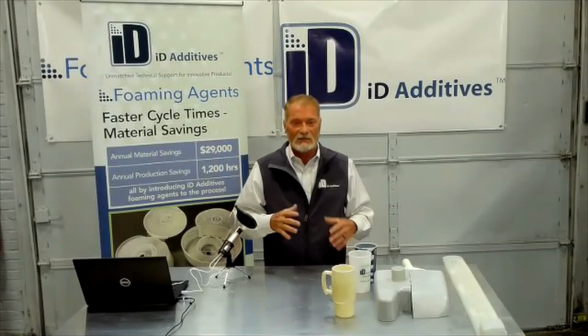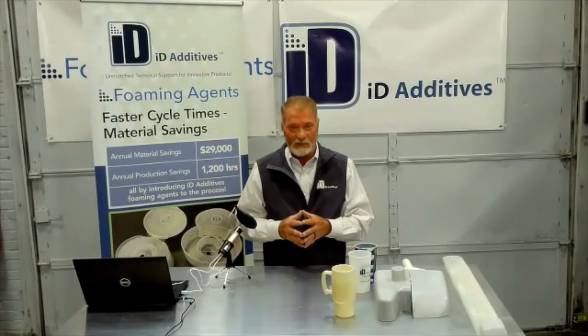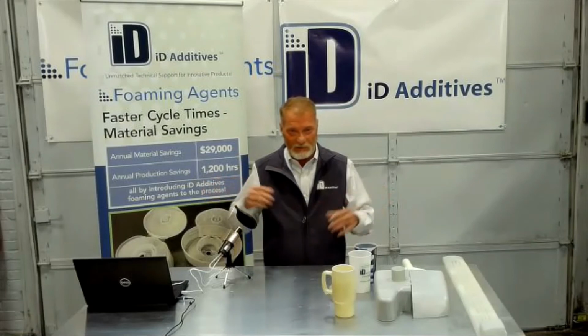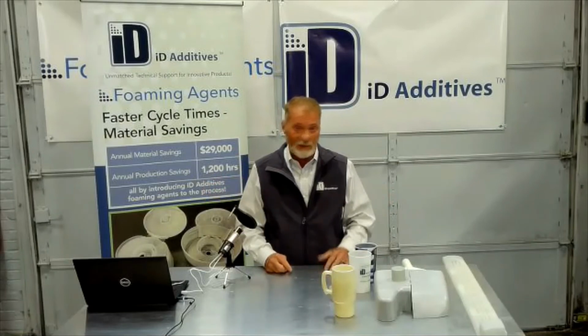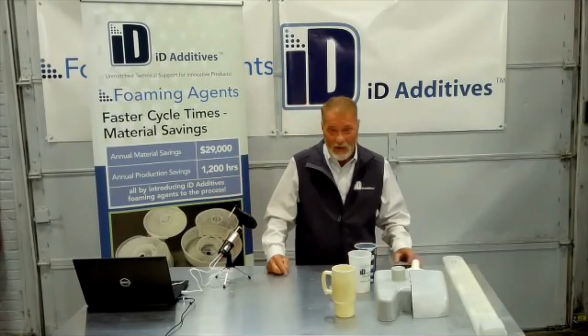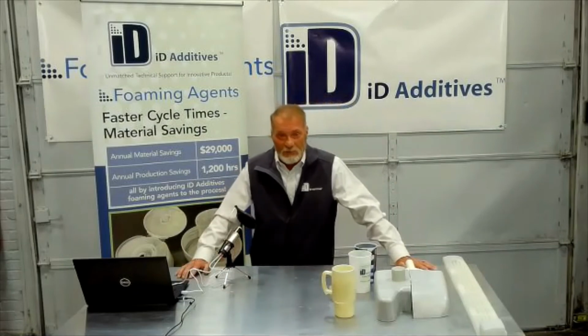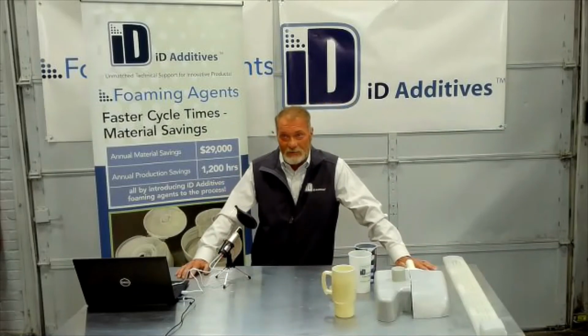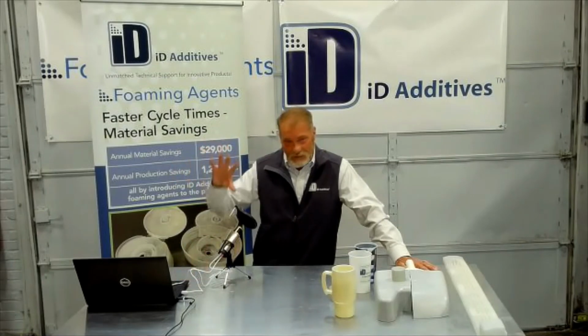See what I'm saying? So balance is really crucial when it comes to foaming and multi-cavitation. Family molds don't really work with foam unless you've got sequential valve gating. Then you can balance it.